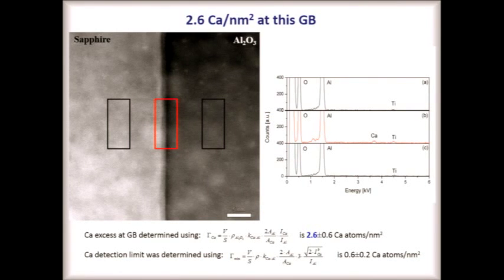And if there was a detectable amount, you remove that from what you measure here in the middle, and then you do the full quantitative analysis. And you can see in the raw data the calcium peak that's at the grain boundary but is not in the individual grains. So it's definitely going there. How much is there? It works out to be 2.6 calcium per nanometer squared, with a detection limit of about 0.6 calcium per nanometer squared.